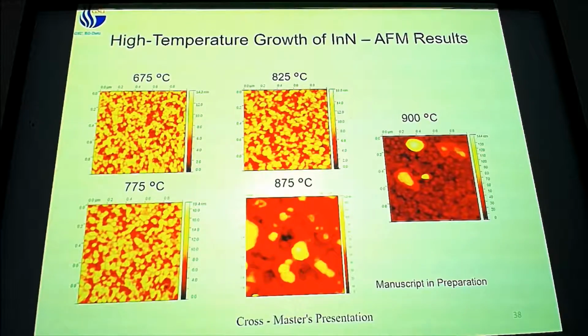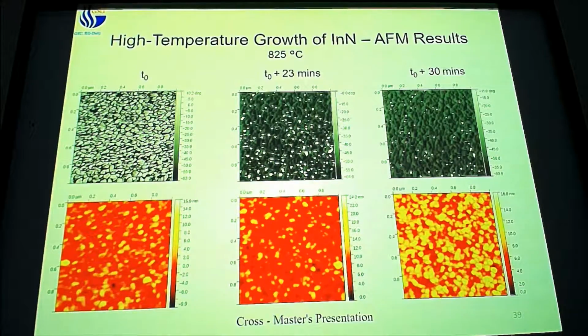Now, during the process of doing this, we came across something else. As I was trying to scan the sample grown at 825 degrees Celsius, we got really, really ugly AFM measurements. A bit of a preface here. Do you guys know what AFM is? AFM is basically a record player, for lack of a better word. It takes a needle and scans it across the surface. And the way that the tip interacts with that surface tells us what the surface looks like. When the tip interaction goes weird, then our surface picture starts looking weird.